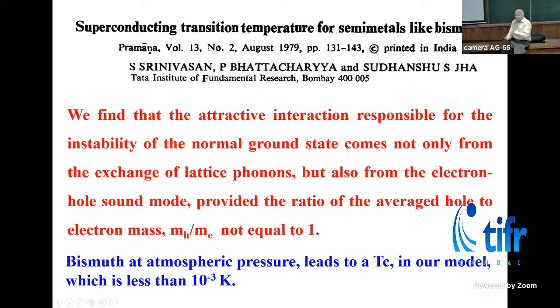Let me quickly move on to some theories. Professor Jha, long back in 1979, did predict that bismuth might superconduct at 1 millikelvin using certain models. When I told him about my results, I said, you have said it's acoustic phonons, but acoustic phonons and plasmons are not there in the system, and the energy range is not there. But we need to check it. So the jury is still open on this theory. They predict the transition temperature should be less than 1 millikelvin. That is what is happening. We need to work on this more, because I would love this theory to succeed more than any of the other theories coming up later.